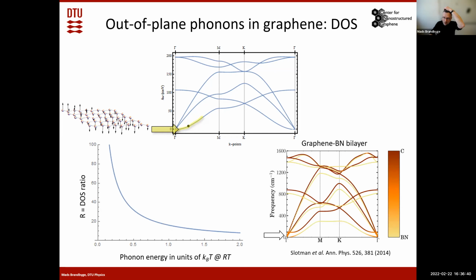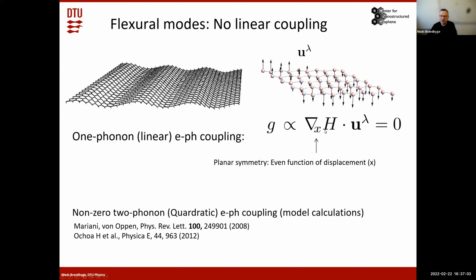And also when you look at stacks, for instance, this graphene bilayer, hexagonal boron nitride bilayer, there you also see this flexural phonon. So we have reason to believe that they still could be dominating in a device. But we also know that if we look at the linear coupling between electrons and phonons, then this would be zero from symmetry if we just look at freestanding graphene.